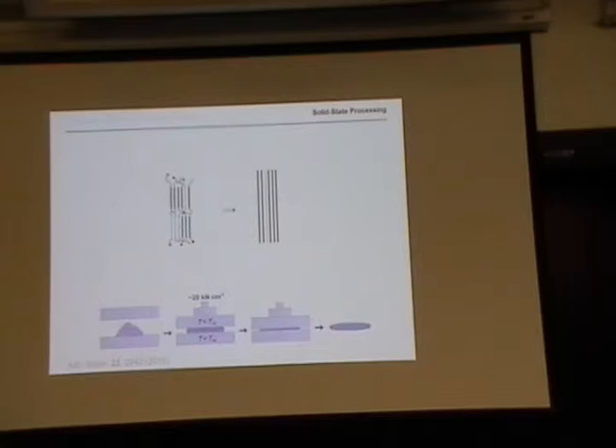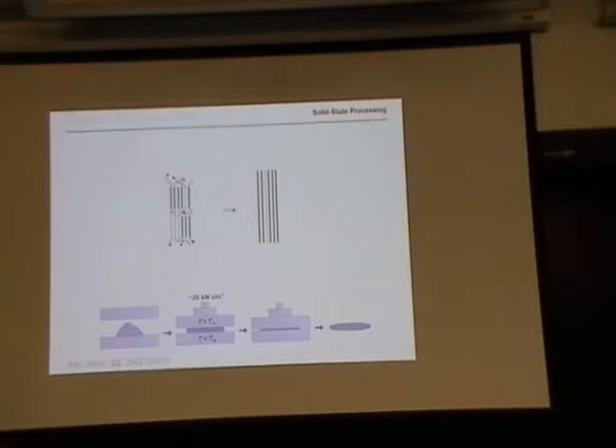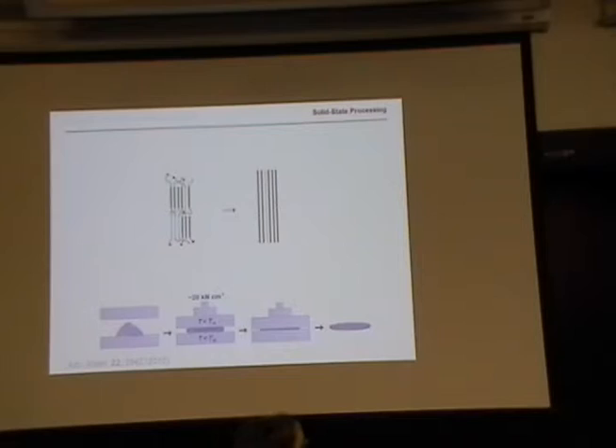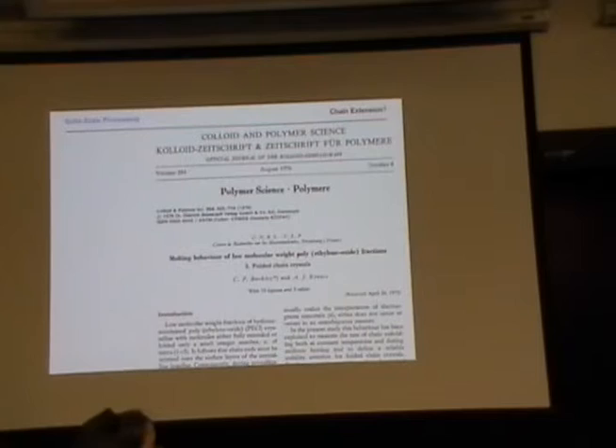I come from the Swiss mountains — it's really like a glacier. Glaciers move and get longer because there's a bit of pressure from their own weight, and therefore it's what is called creep — it slowly elongates over time. Here we do exactly the same: we apply a bit of pressure, maybe a bit of temperature, and we have elongation over time. If you apply too much pressure, you will not get a film — you break it up. You really need molecular movement in the solid state, so the slower you apply the pressure and the more time you give it without degrading your material, the better, and the more the material can stretch out.